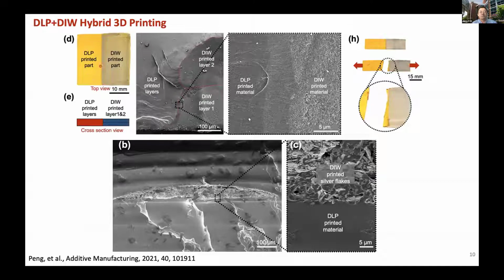In this case, this is a DLP printed part, this is a DIW printed part, and you can see this interface. We put it under the microscope, and you can see this is the DIW layer and this is the DLP layer. The interface is visible, but there's no visible gap or anything in there. This one is actually a silver ink. We printed the silver paste into DLP layers. You can see there are still no obvious gaps between the two layers. In our case, the DLP part is relatively soft. When you stretch it, it breaks in the DLP part, not at the interface and not in the DIW part, because that means you have a really strong interface between the two materials.